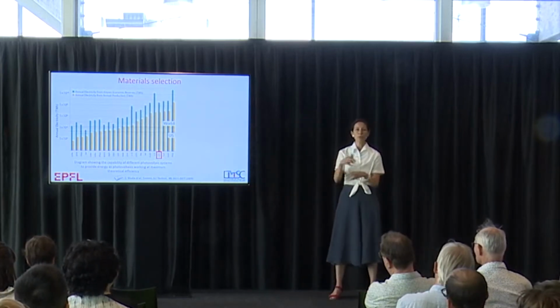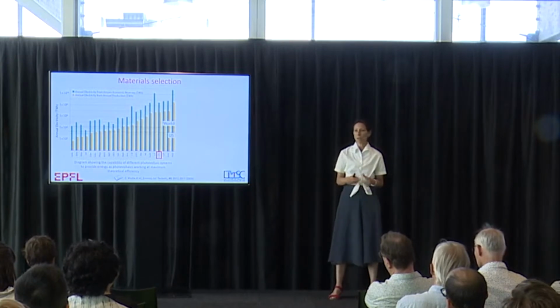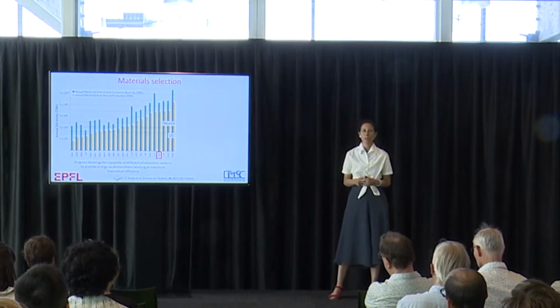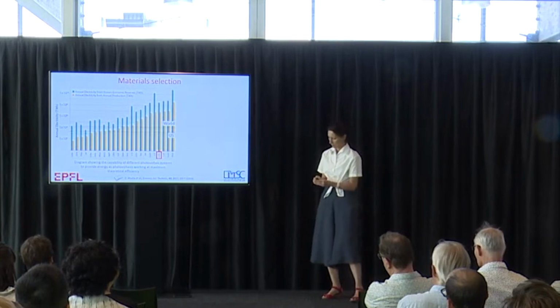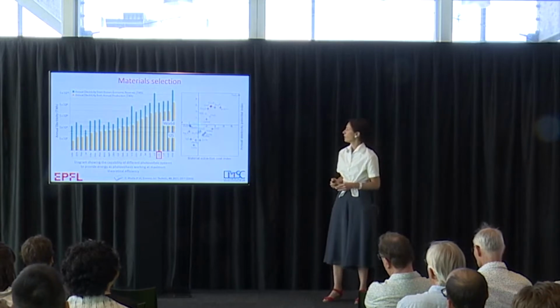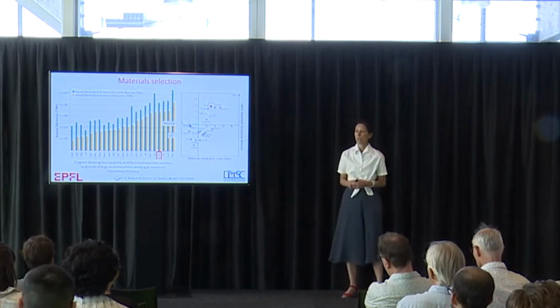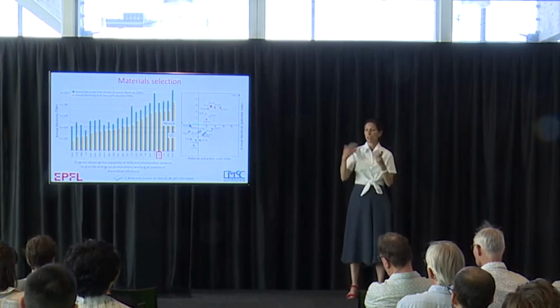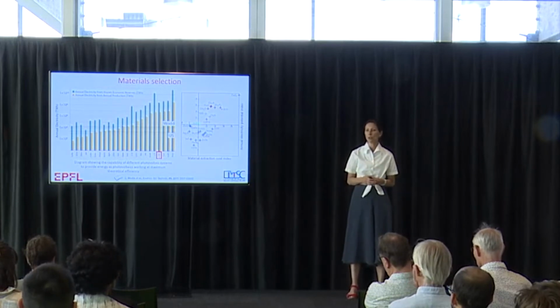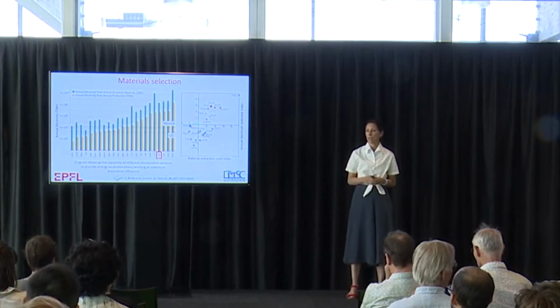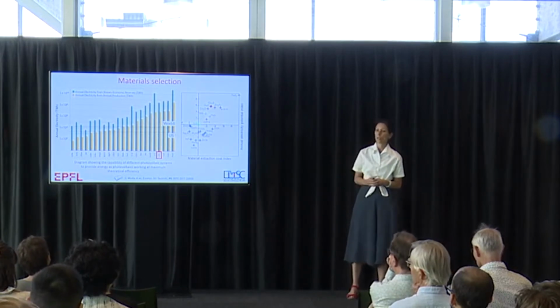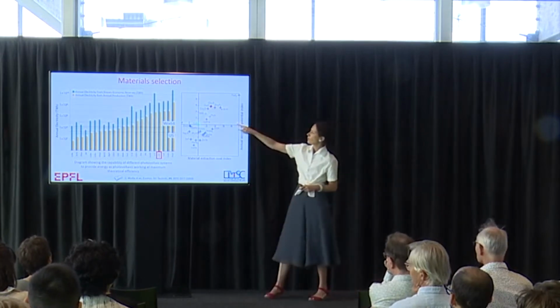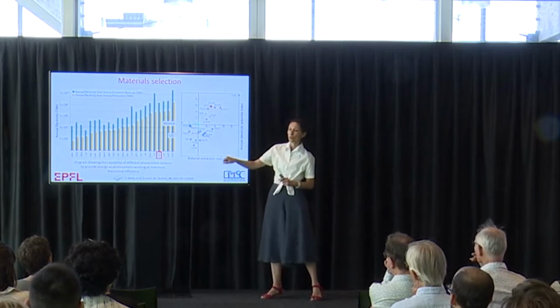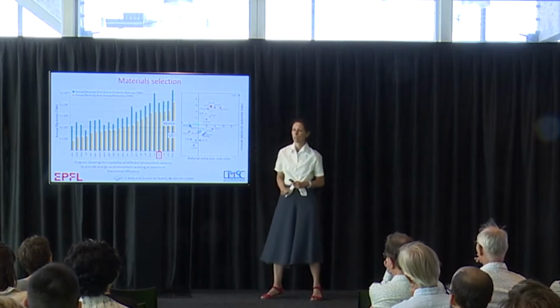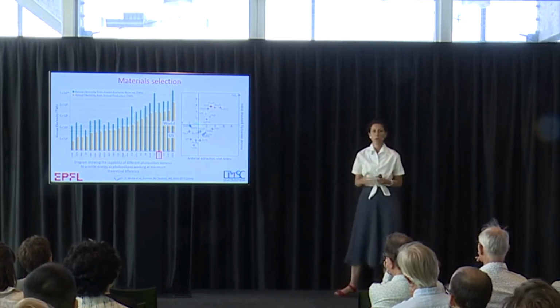They tend to react one on top of another, and having different stoichiometries on a device probably is not a good thing. The same for the copper sulfide. Another way to look at this is you can look at the potential of your material to produce electricity, also in the extraction cost index. And this puts all the materials in different quadrants, and typically you would like to be in this quadrant here. And just for the note, crystalline silicon is here, and it's because of the high cost of purification.